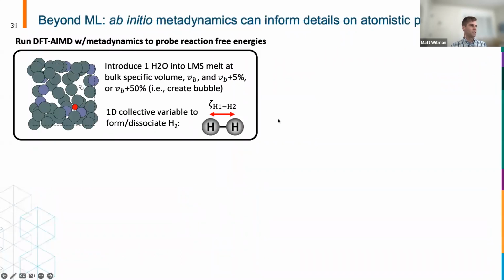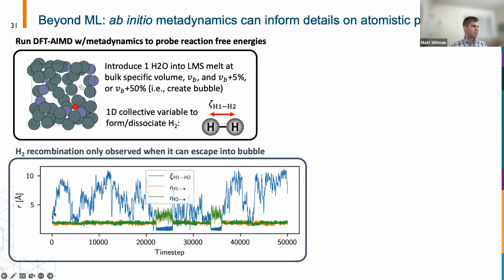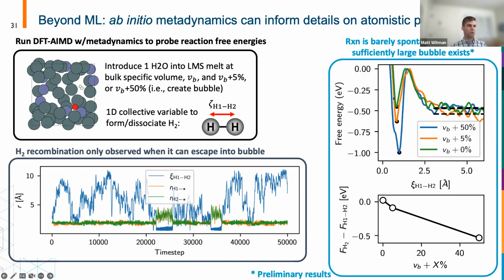So one thing that we're now moving towards is getting some atomistic insights into this process. We've done some ab initio MD simulations where you can create these cells and artificially change the volume to induce bubble formation in the melt. And then you can apply metadynamics to look at free energy barriers of various processes. In this case, we're looking most simply at the association and dissociation of hydrogen in the melt. So you can run these AIMD simulations, analyze the trajectories, and here in blue you're seeing the distance between the hydrogen atoms, which is being biased by the metadynamics, and the distance of hydrogen to the closest metal atoms. And you can see that hydrogen formation is really only occurring and persisting when those hydrogen atoms can recombine on the surface of this induced bubble and diffuse around in that void space. So if you look at the free energy profiles as a function of the density, you can see that you need to actually have this bubble form for the free energy of that process to be downhill.